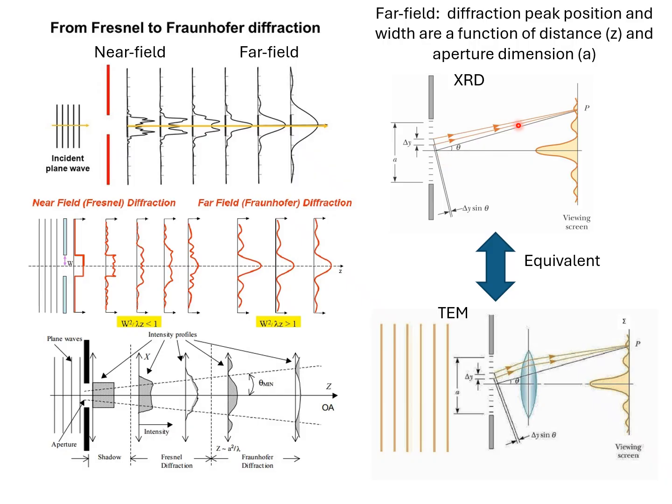If we consider the direct superposition, as would be the case in X-ray diffraction, we could think about this in X-ray diffraction, although this would be a very large angular range and we'd be sampling the intensities. But when it comes to electron microscopy, we're making use of lenses. By using a lens, we can focus rays that are coming off at the same angle to a point on the back focal plane at the imaging plane, where we see a diffraction pattern,